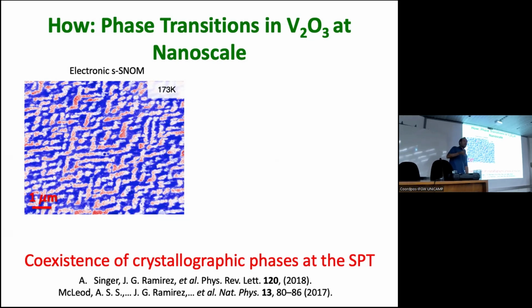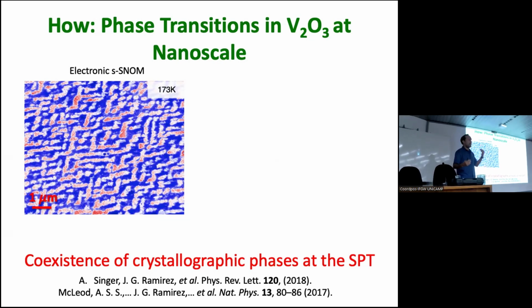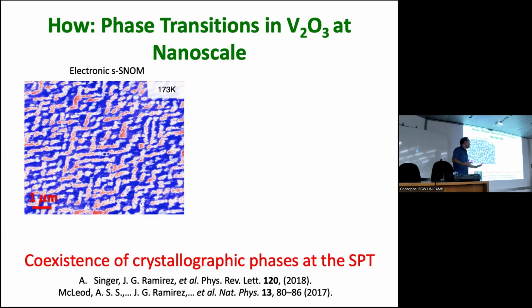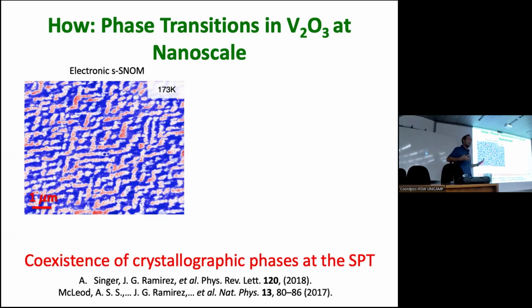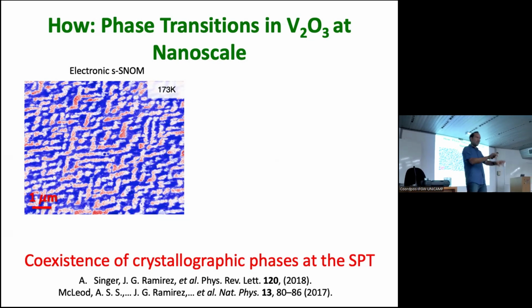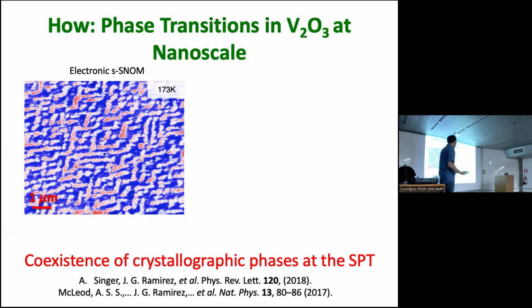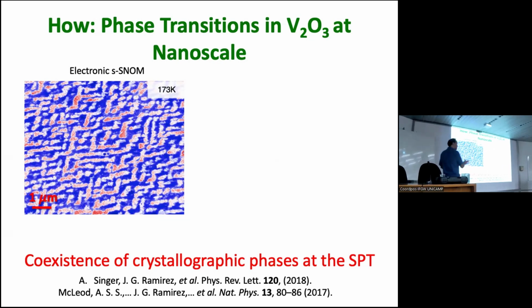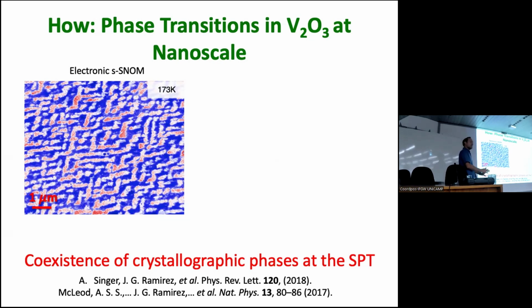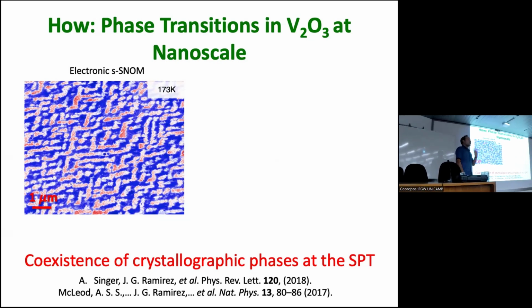And this is something that you expect. You are in the middle of the transition, so you have the coexistence of both phases, the insulating phase and the metallic phase. But what is strange is that this coexistence somehow arrives in a very well-defined pattern that you can see here, which is somehow connected to the way that the crystal structure is changes at the transition. Okay, so the details we can discuss, but the message here is that there is a coexistence of the two phases from the conductivity point of view, or the resistance point of view. There is something metallic coexisting with something insulating.